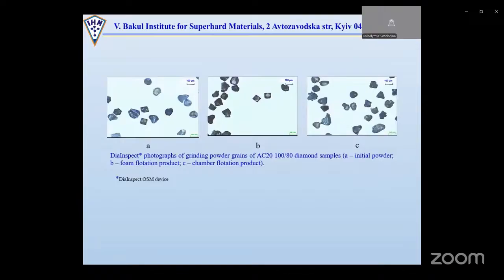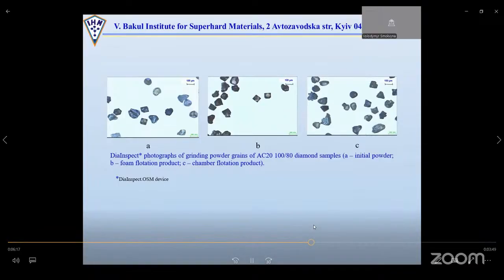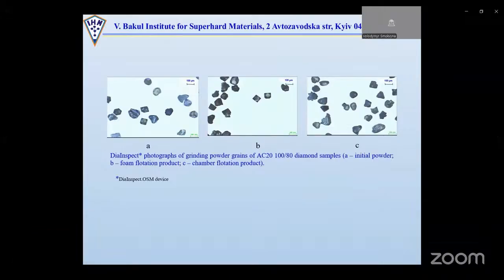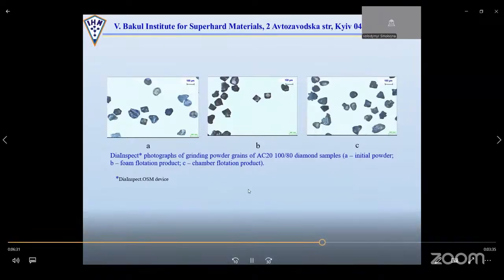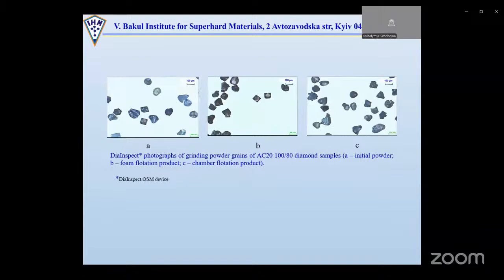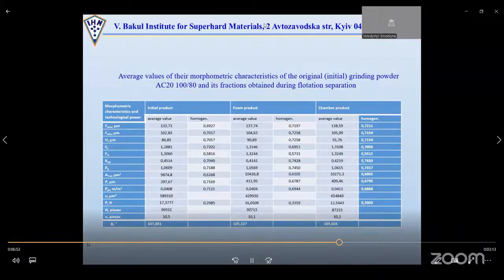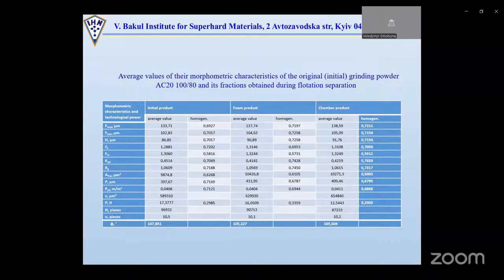On this slide, you can see photographs with morphometric characteristics of grains of diamond powder samples. It's the initial powder, foam flotation product, chamber flotation product. Based on the obtained data, a calculation was made to determine the homogeneity of the studied abrasive powders by morphometric characteristics and by the static strength of the grains using a computer analytical method. And you can see numerical information on morphometric characteristics on this table.